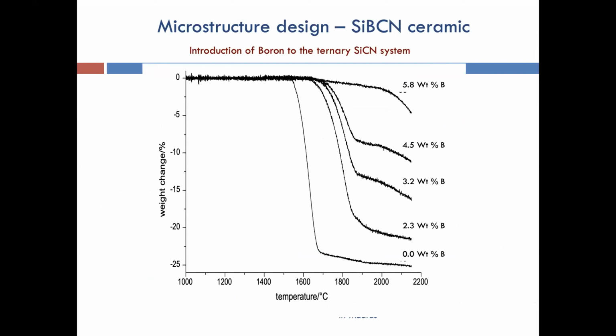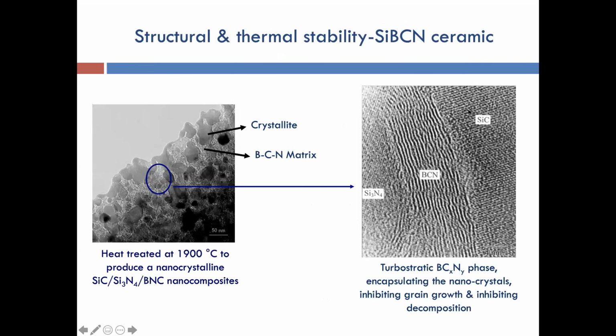Now, if you look at the simple, again, TGA, where the weight loss is recorded as a function of boron content, you can see how, with almost no boron content in the polysilazane, as you keep increasing to close to 6-8% of boron, you have already achieved the target of keeping the material quite stable till 2000 degrees Celsius. And this is the kind of microstructure that I'm talking of. I showed this to you in the second slide. I would like to repeat it once again.